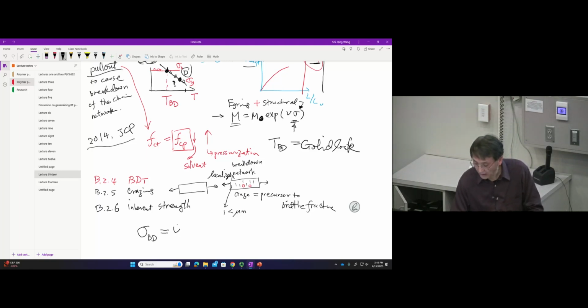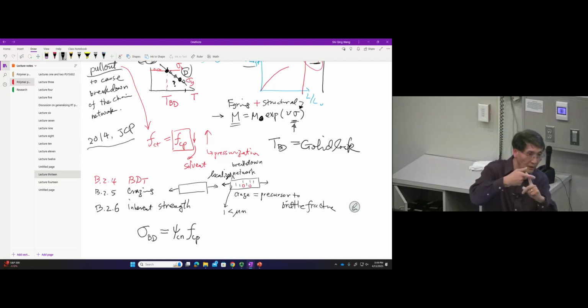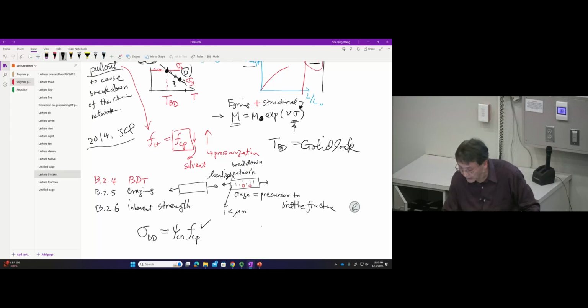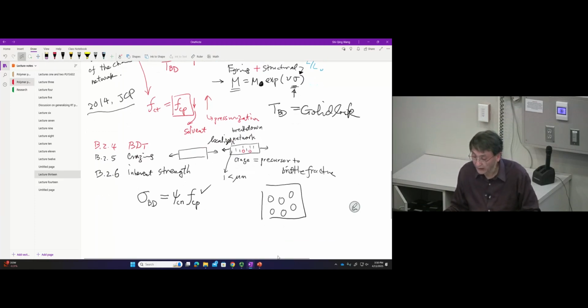If it is, then I can suggest that there is an area density, let's say called chain network, Cn. And then each chain is reaching the force for pull-out. So you go to that critical moment, build enough force, you have to go to that particular transition point. And that's where you're just about to have the sliding, which let me characterize with the tension Fc. And how much resistance does it contribute? It contributes its area density.